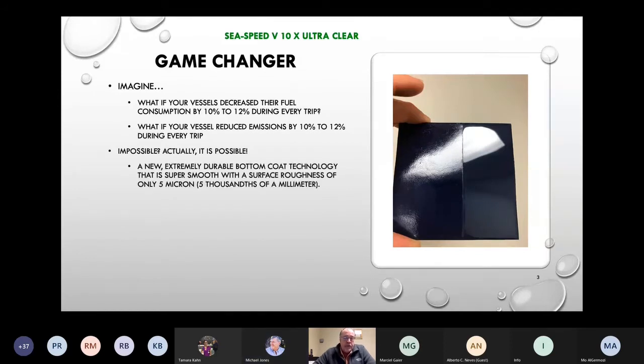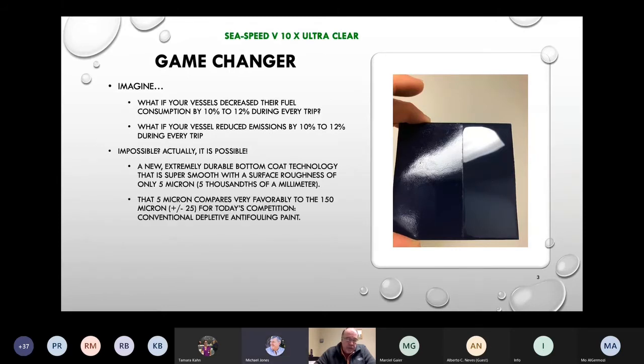We've been around, like I said, 19 years. We've proven this over the years numerous times and with increasing efficacy. So we've been able to get our coating down to a surface roughness of only 5 microns, which is quite smooth. Most of the coatings that we compete against, and I think this goes for all of the 3 companies here, most of these depletive type coatings, the toxic type materials, are typically in the 125 to 150 micron range, which is quite different in terms of fuel efficiency. Basically, for every 10 microns difference in surface roughness, it's about 0.5% in fuel.